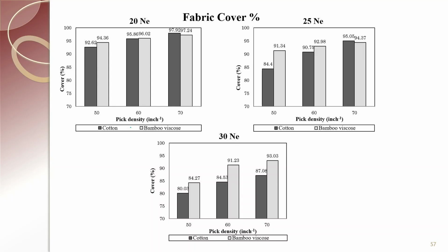Here the cover factor for most of the cases, particularly for finer yarn, we have seen that cover factor for bamboo is more. So, for bamboo viscose, the cover factor is higher than the cotton in general for most of the cases, and the trend is very prominent in case of the finer yarn.